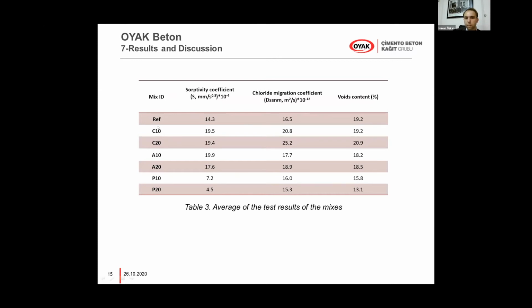If you use a cement replacement of 10% and 20%, the sorptivity coefficient gets higher, the chloride migration coefficient also gets higher, and the void content is nearly similar to the reference mortar. For the fine aggregate replacement, sorptivity and chloride migration coefficient are also higher than the reference mortar, but better than the cement replacement, and void content is nearly similar to the reference mortar. Finally, paste replacement gives the best results overall, because as you can see here, there are more than 50% lower sorptivity coefficients, and chloride migration is lower than the reference mortars, and void contents are also lower than the reference. And these are our test results.